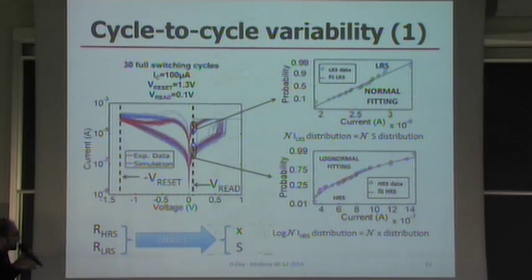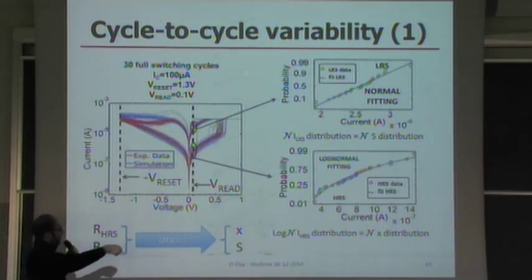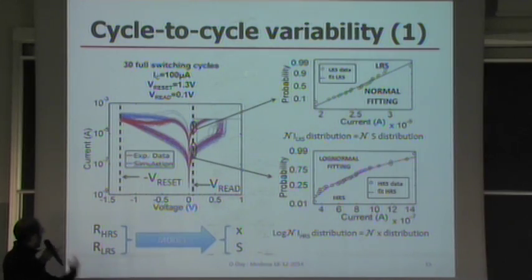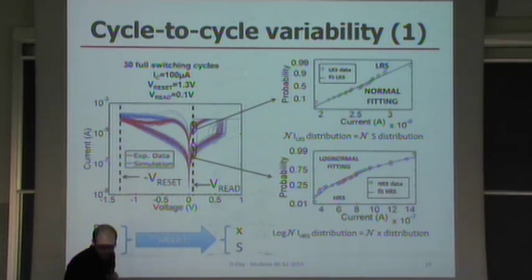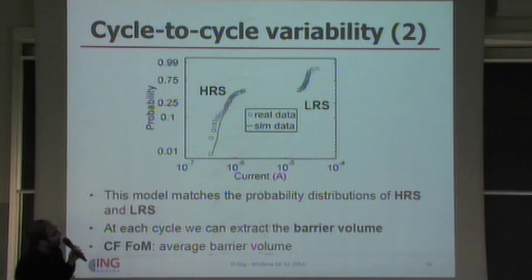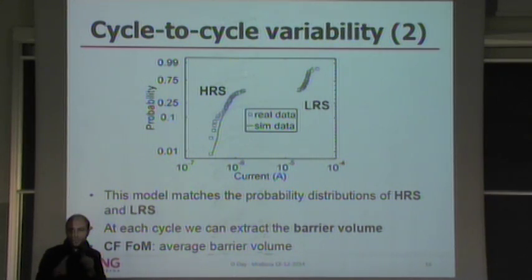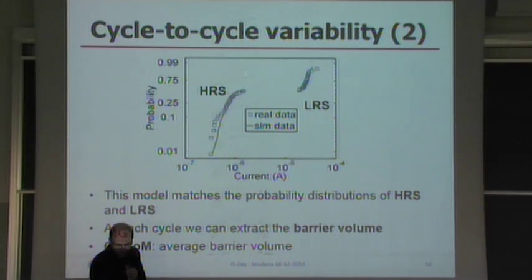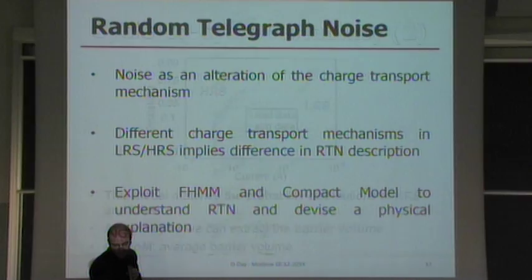Indeed. And if we exploit the model to relate the resistances to the physical characteristic, we may end up actually simulating the cycling variability, and that's what we did. So with this model, we can really capture the essence of the cycling variability so that we have a compact model which is variability aware, and we can exploit it to have variability aware circuit simulations. And this is the whole thing about cycle-to-cycle variability. So we successfully included it into the compact model.